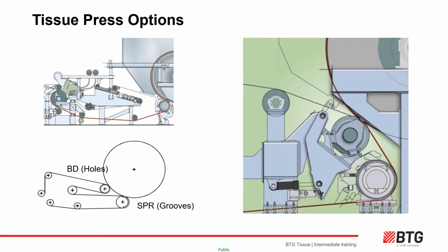Shoe press machines can facilitate better creping efficiency through generating higher MD stretch, allowing lower crepe ratio, hence higher reel speeds and increased productivity. There is of course limited space available to fit in one or two presses or a press and a suction roll and still take maximum advantage of the full drying capacity of the Yankee circumference and hoods. Therefore the dwell distance between the press nip and Yankee coating shower is at a premium.